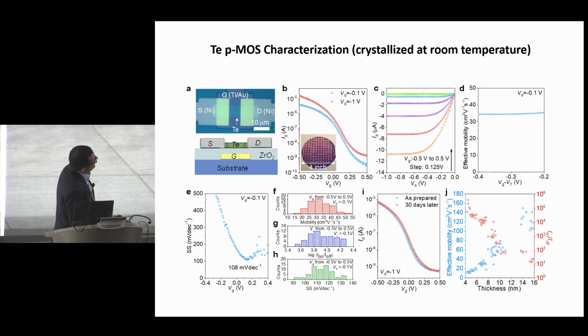And specifically, here I'm showing you some of the PMOS devices that we have built. The effective mobility is about 30 centimeters squared per volt second, which is, of course, much lower than silicon, but this mobility is pretty competitive if you think about oxides. And many oxides are being used as N-type devices. So this is a P-type device. This is analogous to oxides, but it's now for the PFET.